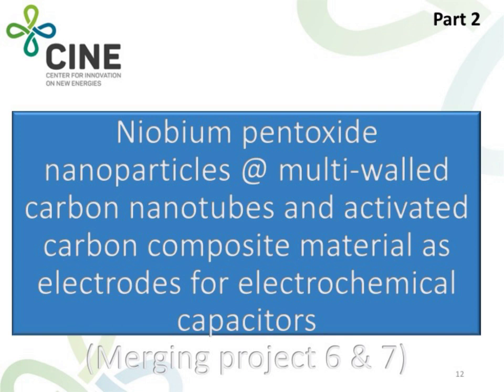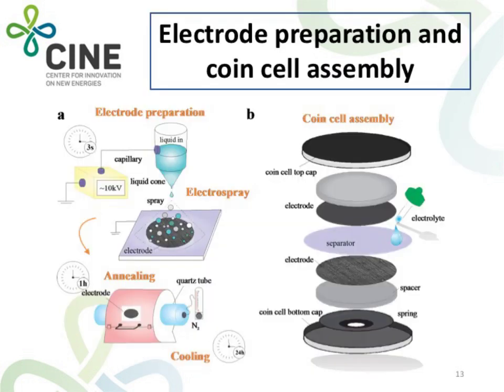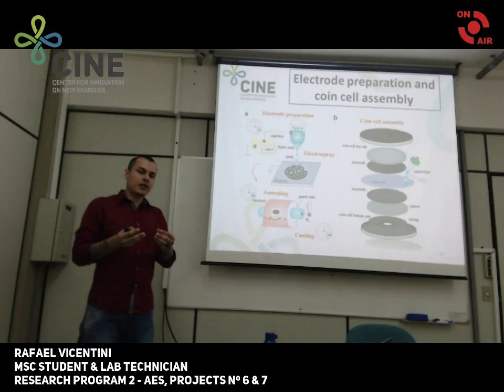In a similar process to that described in part 1, but now merging Project 6 and 7, we present here a carbon-based material decorated with niobium pentoxide. But now, the carbon material is composed by carbon nanotube and activated carbon. Then, using together carbon nanotube and activated carbon, we can improve the electrical conductivity, the chemical stability, and mainly the cyclability of these carbon-based electrodes.